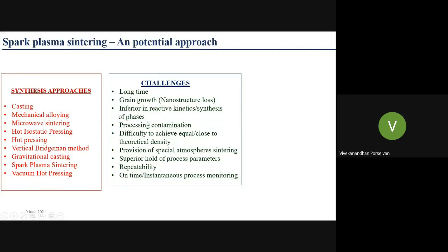Contamination is one of the crucial things, because in semiconductors contamination is undesirable since it significantly affects performance. There is also difficulty in achieving equal or close to theoretical density, because if your material has porosity, what will happen? That is a defect that will scatter your charge carriers, that is electrons or holes. Provision of a special atmosphere during the sintering is very, very important, right? Because if you want to overcome atmospheric contamination, we have to conduct the sintering process in a closed or some kind of special atmosphere, that is an inert atmosphere provided with helium, nitrogen, argon, and so on.